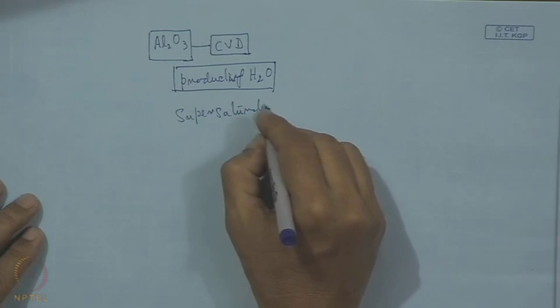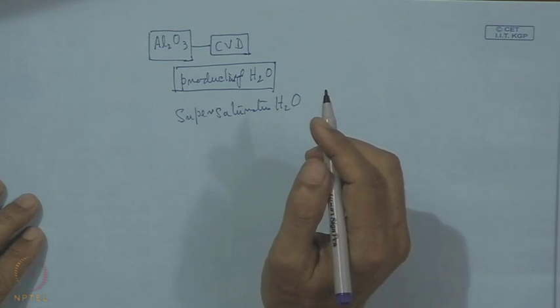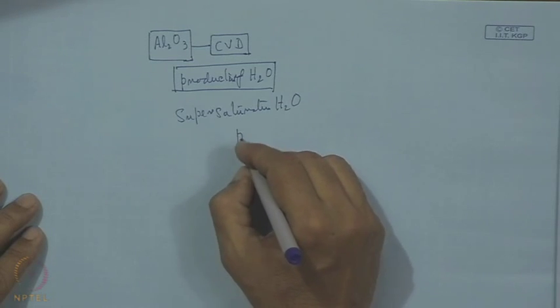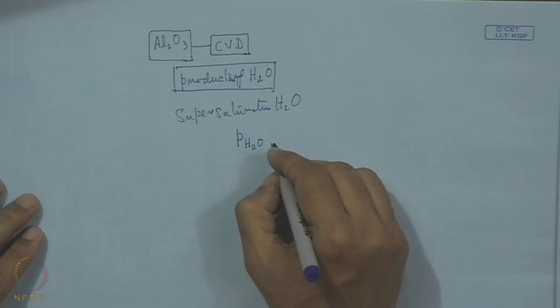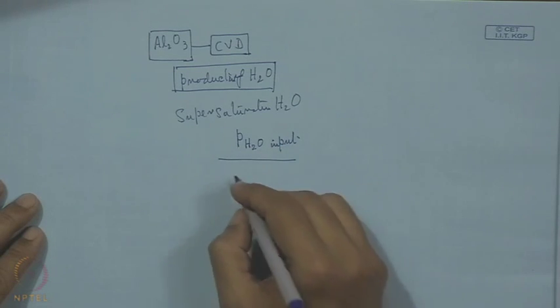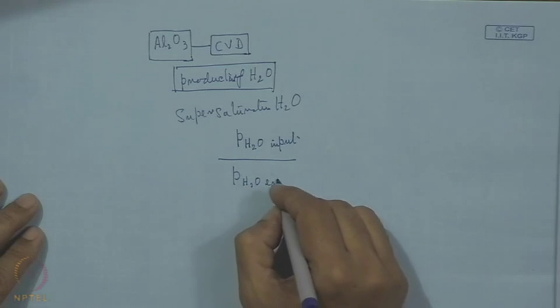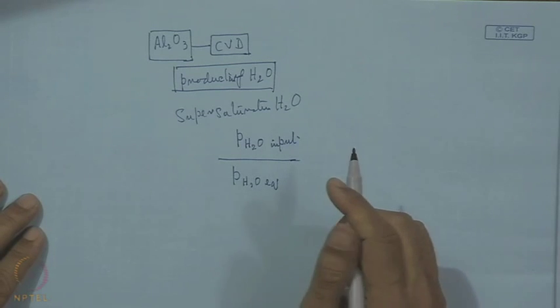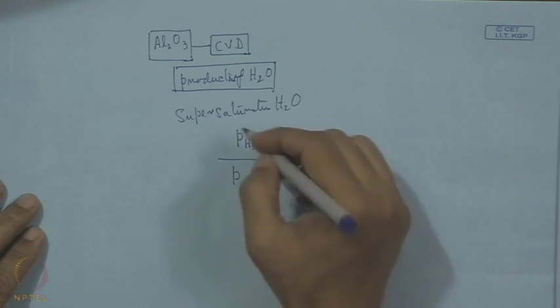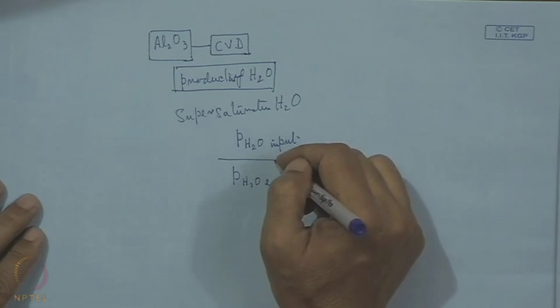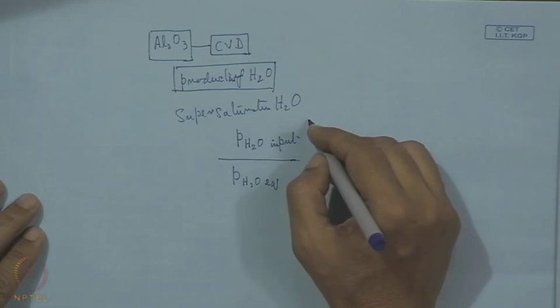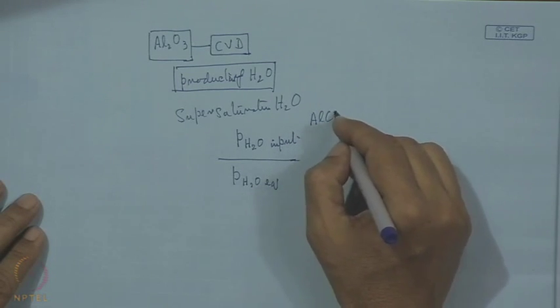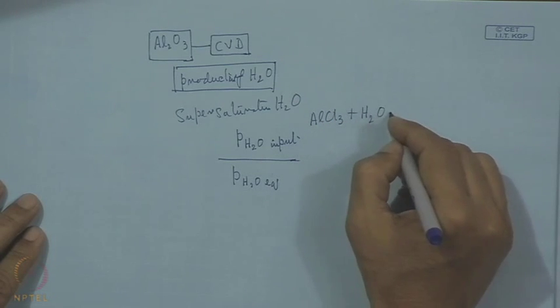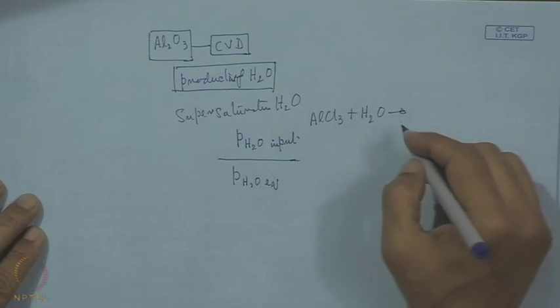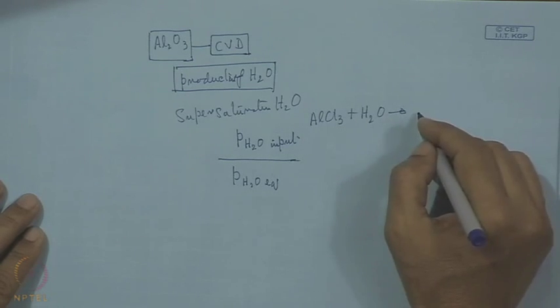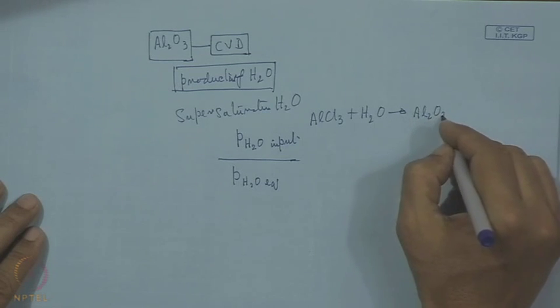Supersaturation of H2O means the partial pressure of H2O, which is the input partial pressure, divided by pH2O in the equilibrium. So, the objective of CVD should be to make this ratio, which is the index of supersaturation, as high as possible in order that this reaction, AlCl3 plus H2O, which is nothing but hydrolysis of AlCl3, goes at a faster rate in this direction with the result of Al2O3.